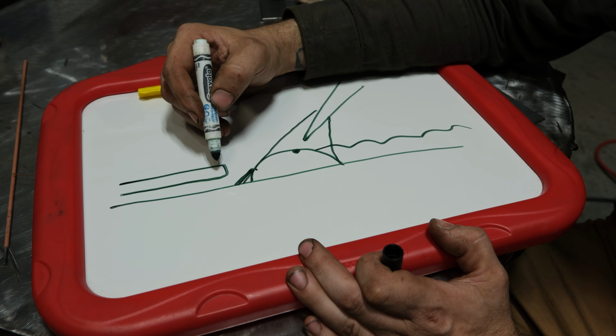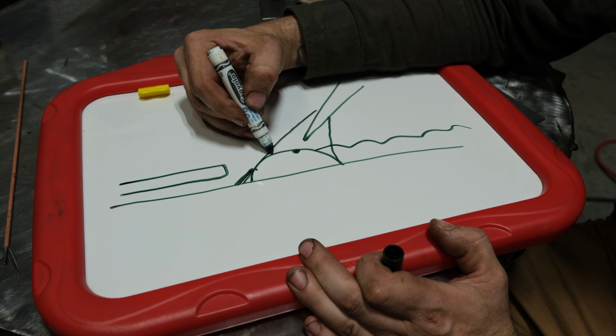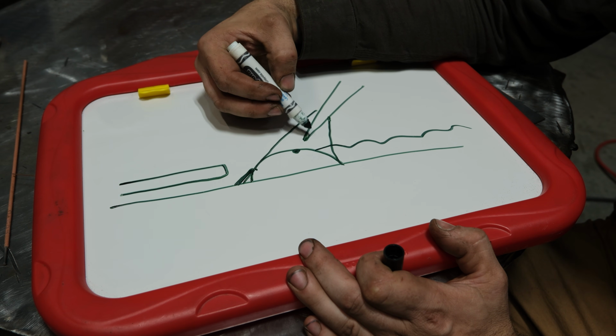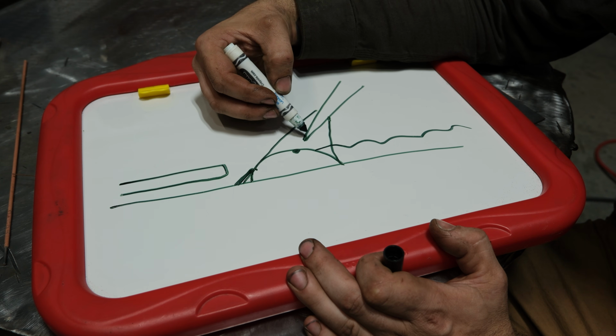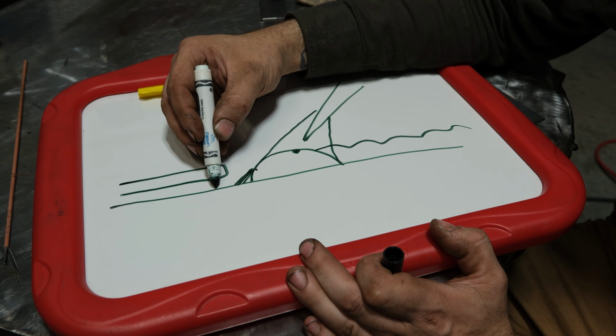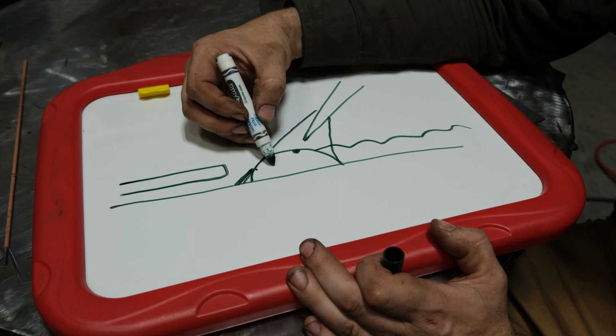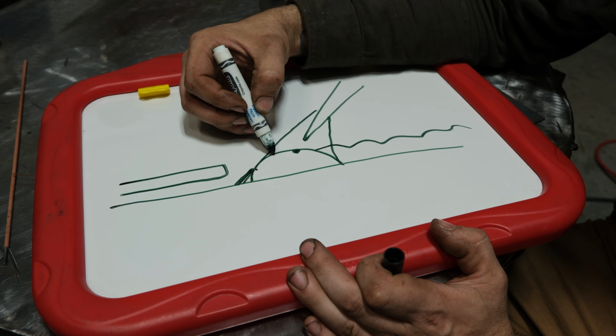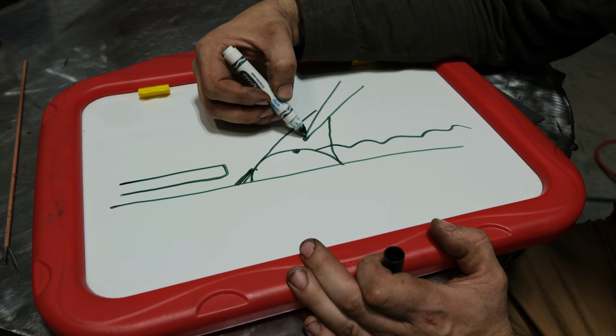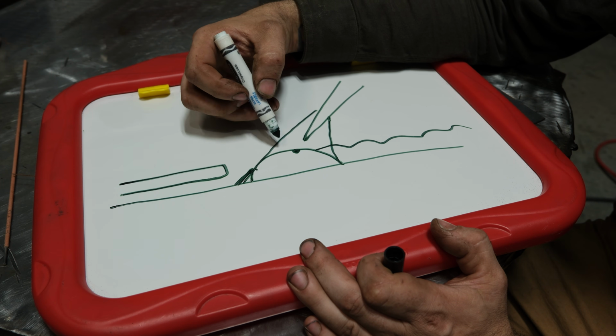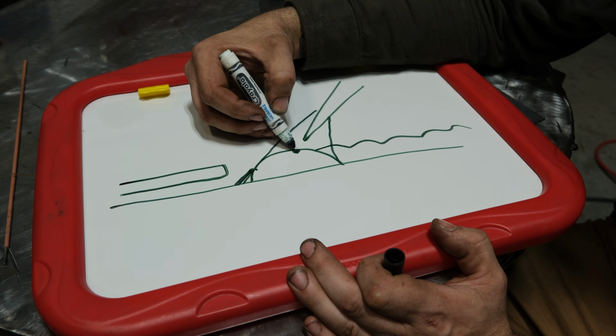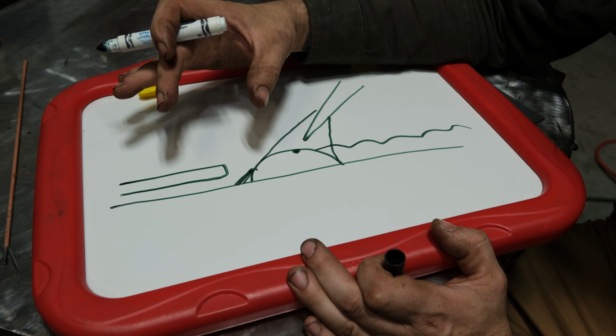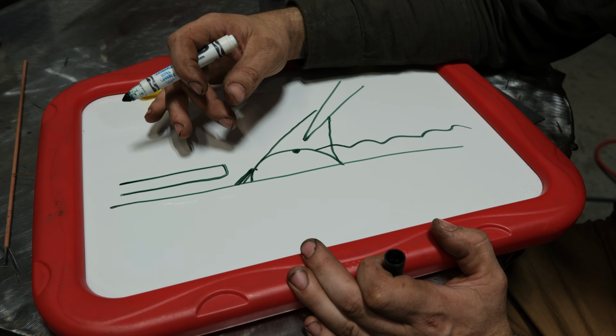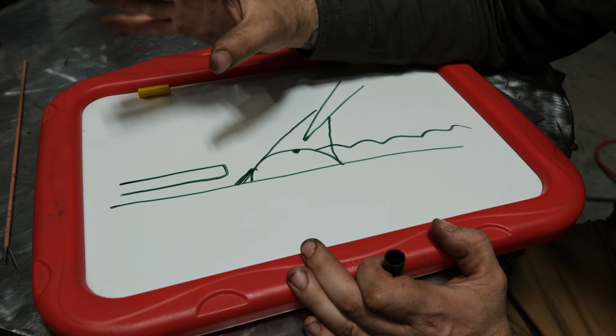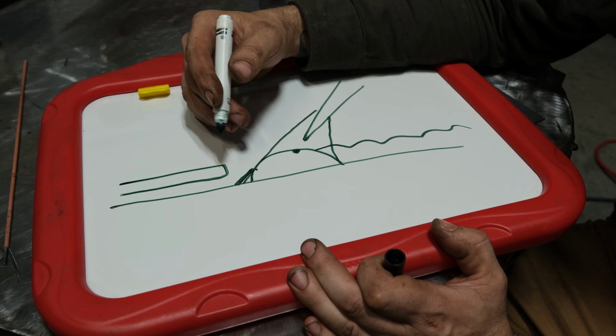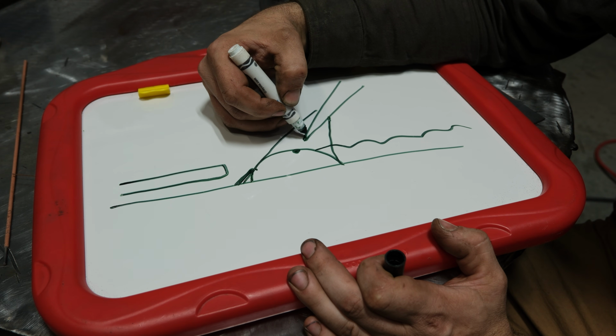And what you're going to find, and I'll draw like I'm welding this so we have metal deposition, when you add filler, the molten pool rises. One of the reasons why when you're inexperienced you dip the tungsten so much is because you're holding that arc gap to the plate, right? Well, as you add filler material, your weld rises off the plate directly into your tungsten. So one of the things you have to learn and master when adding filler material is you have to hold a slightly longer gap. And guys, I'm not joking when I say this. You're talking like minuscule, like half a millimeter more, or about a 64th or a 32nd of an inch. Very little bit do you need to increase the arc gap.